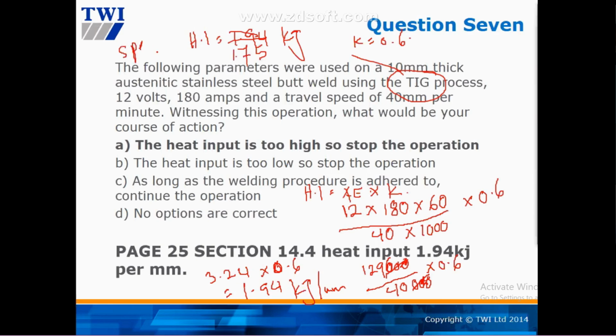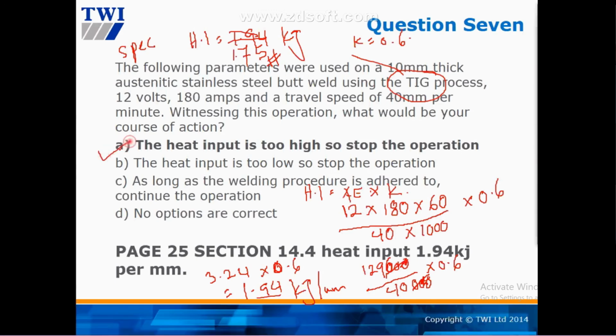All right, the spec only requires a maximum of 1.75, where during welding, when they record the parameters, they found out that it's more than 1.75. In this case, we got 1.94. So that is higher, right? So that's where the answer goes to A. All right, got it?